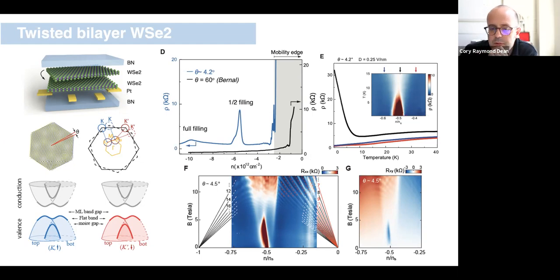So I'll get to a moment maybe why the half filling peak is larger than the full filling peak, for those who have that question. So here when I say half and full filling, a little bit the nomenclature wandered over time. I want to be sort of clear about this. So in our system, we have a twofold degeneracy. So full filling corresponds to exactly 2 holes per Moiré unit cell. And here, if I refer to half filling, what I mean is 1 hole per Moiré unit cell. That's the condition I'm in.